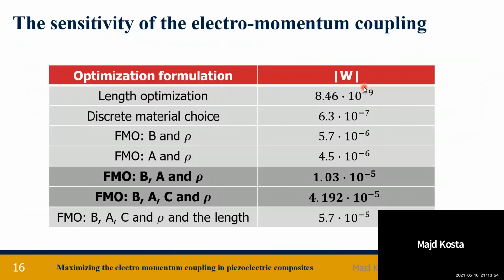We did the same process for other couples of properties. And in this table, you can see a conclusion of all the results that we have obtained. We highlight in here 2 rows, you can see it in here, where we also note that if you optimize over B, A and rho or B, A, C and rho, the results are not far away from each other, which means that the sensitivity of W with respect to the material stiffness is not significant.